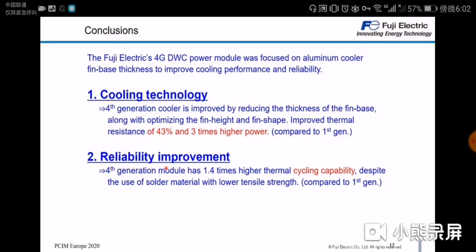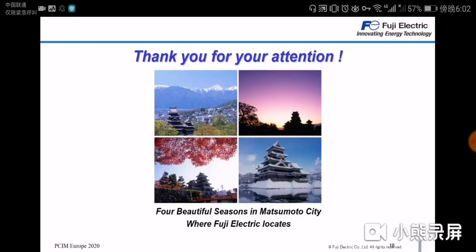The reliability improvement is also significant with 1.4 times higher thermal cycling capability, despite using a solder material with a lower tensile strength.